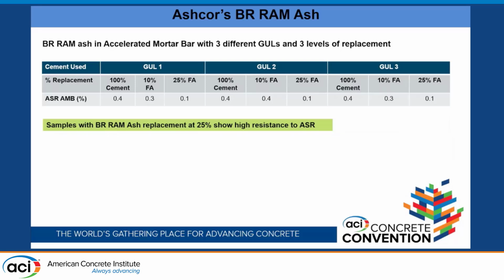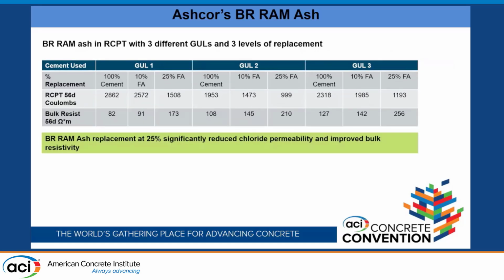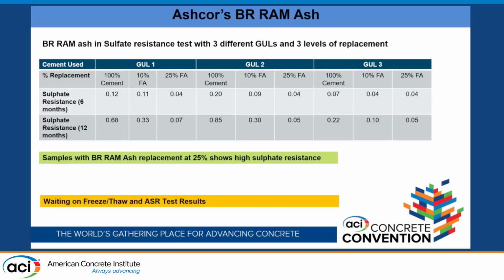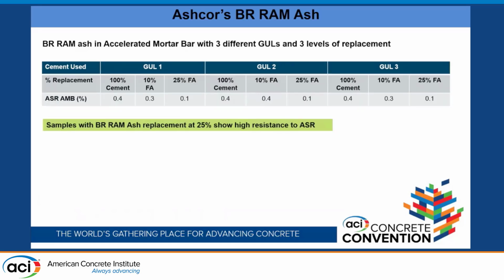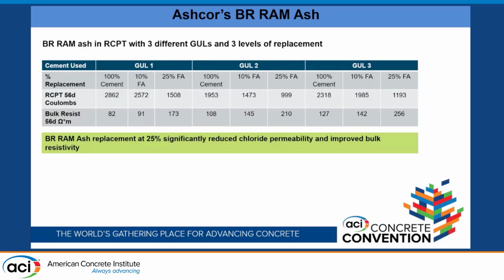Here are results of the accelerated mortar bar test, the ASR test. The control, 10% replacement, and 25% replacement. As you can see, at 25% replacement, concrete shows high resistance to ASR. Results from RCPT and bulk resistivity, again, at 25% replacement, significant reduction in chloride permeability and improvement in bulk resistivity.